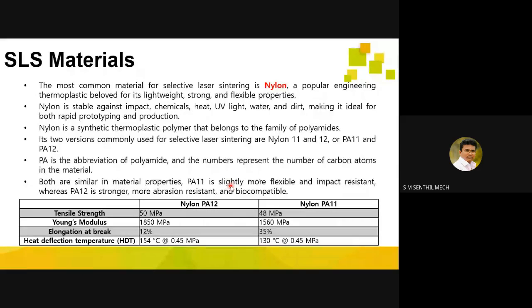Here you can see a table with relative characteristics between nylon PA12 and PA11. Both have similar strength values: PA12 has 50 megapascal, whereas PA11 has 48 megapascal. Both are more or less the same.